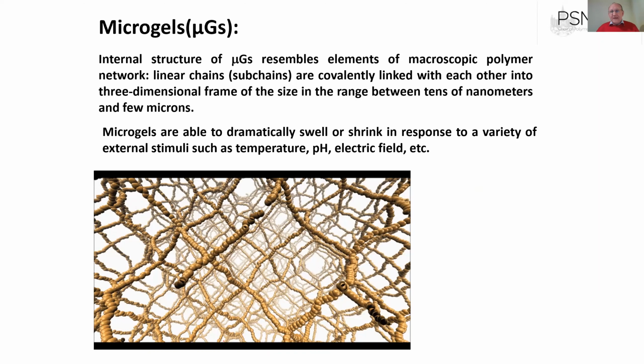Like in the case of macroscopic gels, the most spectacular property of the microgel is the ability to swell and collapse in response to the variation of external conditions, like temperature, if we deal with, for example, PNIPAM or PVCl microgels, or via changing of pH, if we deal with microgels on the basis of weak polyelectrolytes. In computer simulation, this is the picture we would see if we could look inside the microgel, and this is a swollen state.